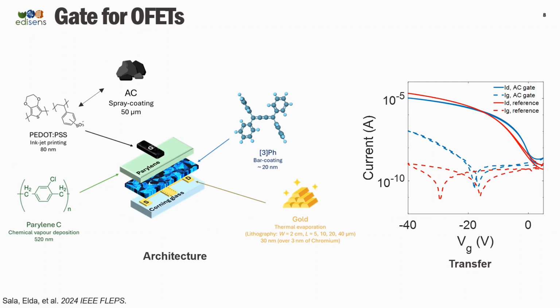So for the transistors, we use an architecture that we already have in our lab using [3]Ph as a semiconducting material, and this is already published and working with PEDOT. And what we have done here is we have changed PEDOT with carbon, with this gelatin and carbon ink. And as you can see here, the characteristic is pretty much the same, meaning that the material is effective in gating a transistor. And the carbon material as a gate material is very useful because the surface area is very high. So you can use it for functionalization purposes, for example.